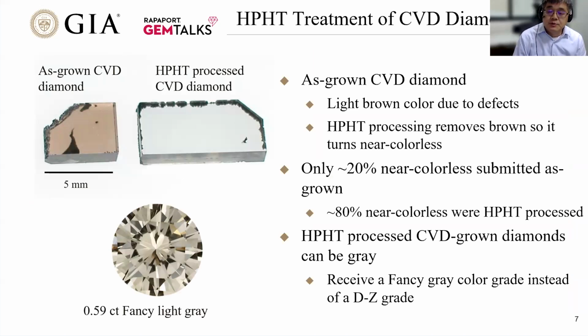Here's an example we tested as early as 2003. This is a single crystal CVD diamond we cut into two pieces. The left side, brown color, we kept as a reference, and the right side is after HPHT treatment. Color appearance has been dramatically improved, but if you pay a little bit of attention, it still has a bit of a grayish color after HPHT treatment.